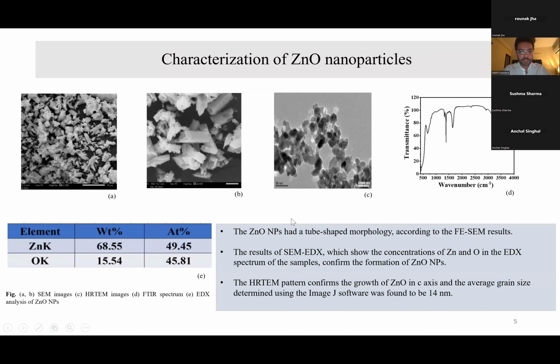After this, coming to results, this is the characterization results of the zinc oxide nanoparticles. So with the FESM results, we got to know that the zinc oxide nanoparticles had a tube-shaped morphology. With the SEM EDEX concentration that we evaluated and found, the zinc and oxygen concentration proved that the zinc oxide nanoparticles were formed. The HRTEM pattern confirms the growth of zinc oxide nanoparticles in the C-axis, and the grain size was obtained to be 14 nanometer.